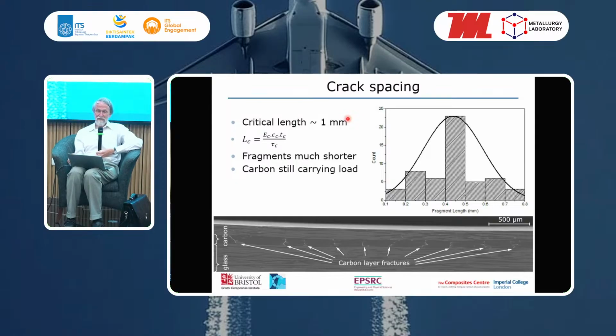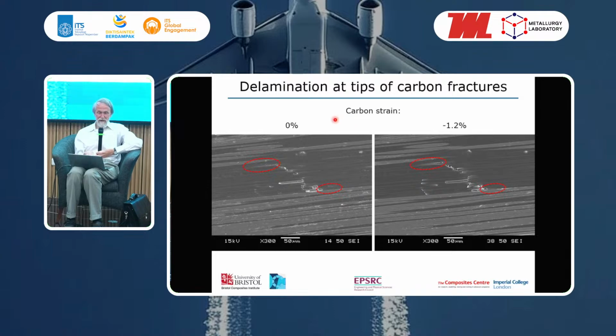And you can see that in some of the microscopy of these specimens. If you look at this one here, you see there's a crack in this M55 ply at about 45 degrees, and there's some local delamination. So this is with no load, so it's been loaded up and then unloaded, and this is what it looks like. But if you reload it again up to 1.2% strain, you can see that that delamination has opened up a little bit. So there's a delamination here which opens up under load, and that's what gives you this appearance on the surface where you see these yellow patches, because you have this localized delamination. But the plies are very thin, so that delamination does not propagate.